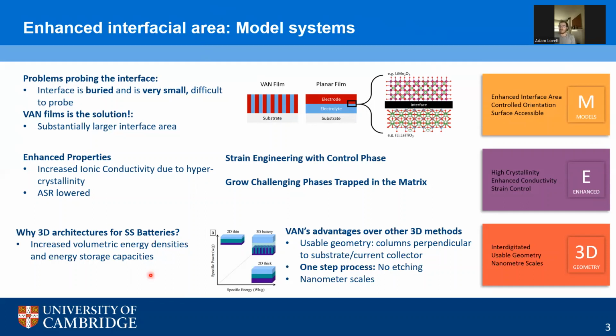But why is VAN unique over other methods? Well, first of all, we have a usable geometry because our columns are perpendicular to our substrate. But VAN is also a one-step process. We don't require etching. We can just grow our 3D architecture in one go. And we get nanometer scales, with the columns typically being on the order of 10 to 50 nanometers in diameter.